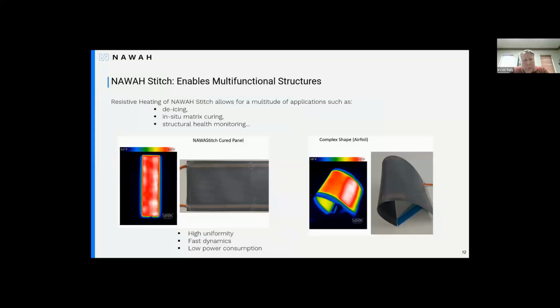To emphasize this, the panel on the lower left was a fiberglass panel that we completely cured under a vacuum bag by putting an electrical current into it. There you can think of things like tool faces, field repairs. The one on the right is a wing leading edge. We were able to build the leading edge, put the carbon nanotubes in it, and put an electrical current in it to shed ice. We've done that with a propeller blade, and there the one test we had to pass was to run it for 24 hours nonstop, draw less than 20 amps of power, and keep it at 125 degrees for an anti-icing mode.